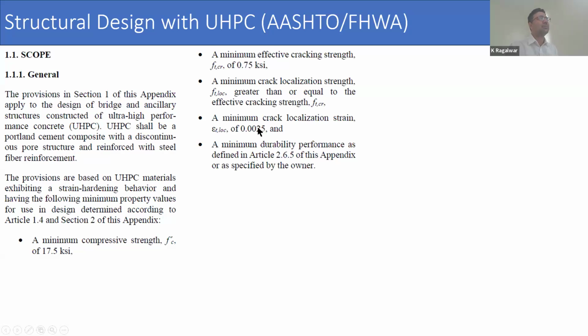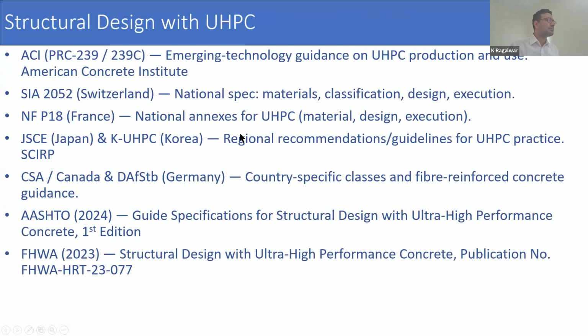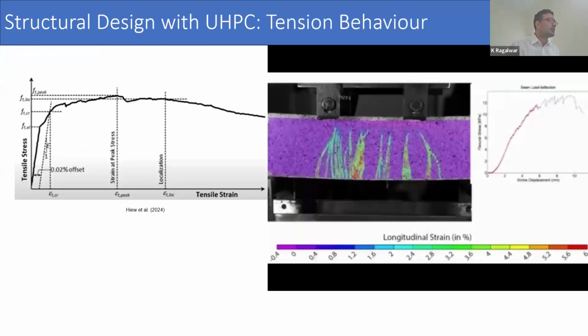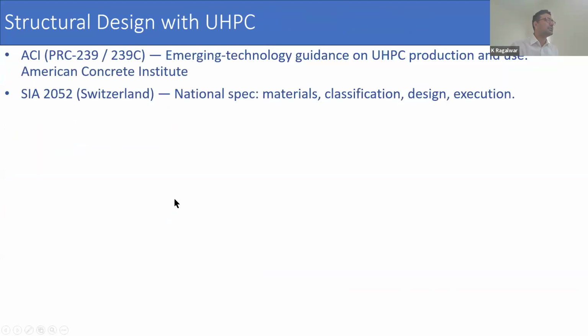So it cannot be strain softening. That means a crack happens and then tensile strength continuously dips down. That is the kind of material we cannot use this guideline for. And then a minimum crack localization strain is also defined. So if we look at this video here that we talked about, this is localization, where one crack opens up, and then the strain related to that location is known as localization strain.